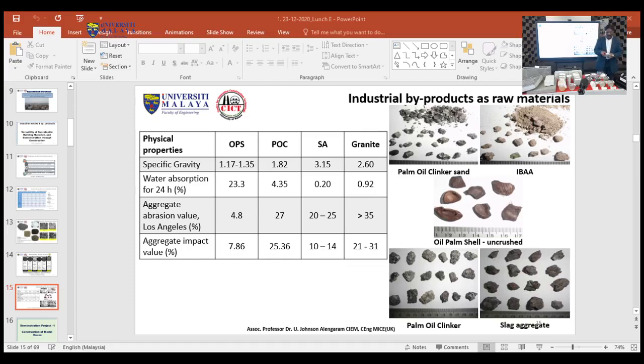Also, we have palm oil clinker aggregates. These aggregates are very porous and very lightweight compared to the slag aggregates. This can be utilized because of the minute pores or bigger pores in this particle.